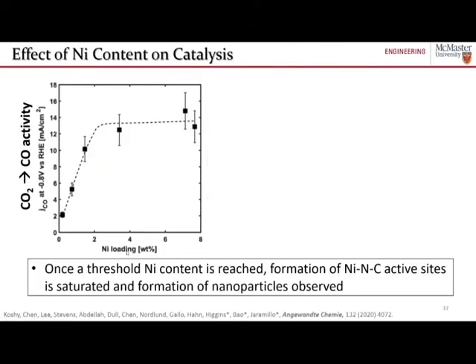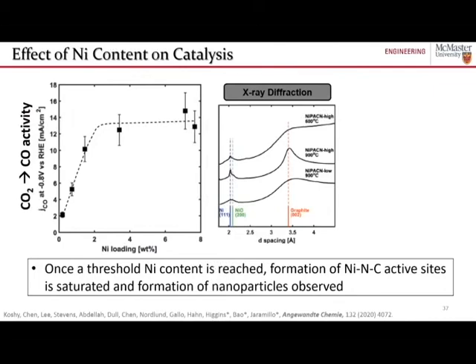Another thing that we did is we systematically varied the amount of nickel that we put in these catalyst materials. And what we found is that when we increase the nickel content up to a certain amount, the activity for converting carbon dioxide into carbon monoxide saturated at about 3 or 4 weight % nickel. And what we think happened there is that ultimately we hit the saturation threshold of these atomically dispersed nickel sites in the carbon material. And after that, we started to see the formation of nickel and nickel oxide nanoparticles.